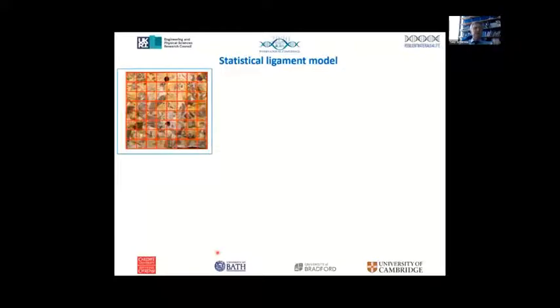And this is all to do with this. Imagine you've got a crack. It's concrete, and you can see here two holes where healing agent has been fed in. And the brown bits are where it's recracked and you can see healing agent was, and the other bits are where either the crack's gone somewhere else or the healing agent didn't quite get there. In this case, it's where the crack's gone somewhere else. Now, if you went through each one of these little blocks and measured the strength of it, first off, before it cracked, and then after it had cracked, you'd get a kind of statistical distribution of cracking, okay?